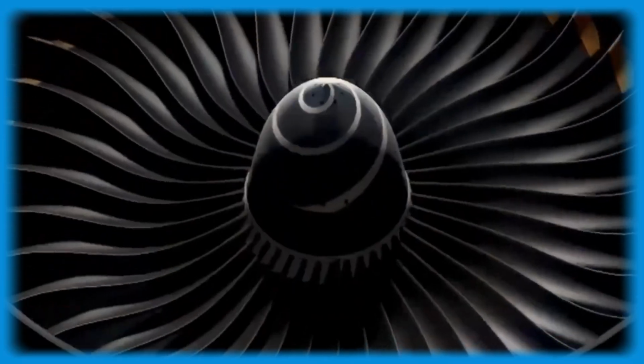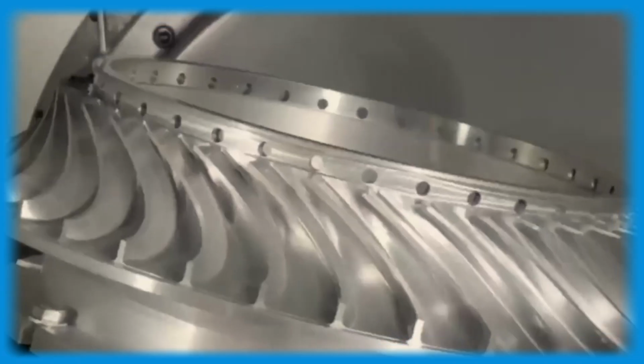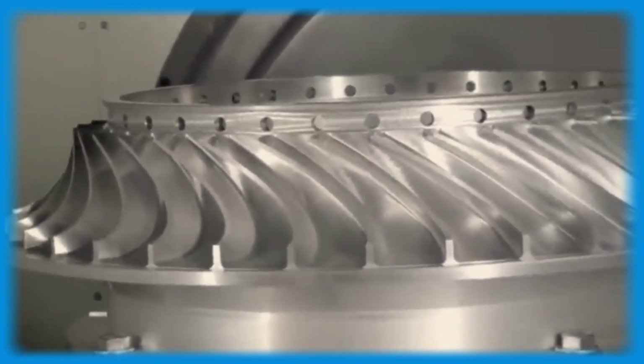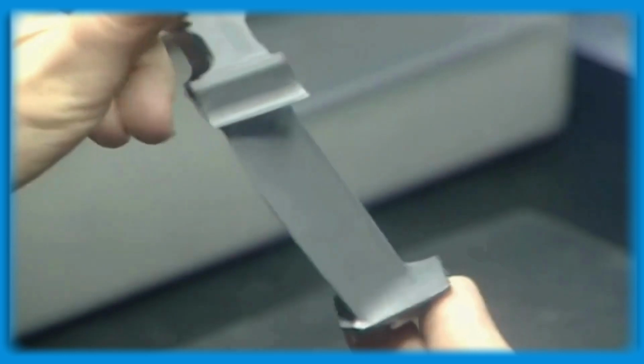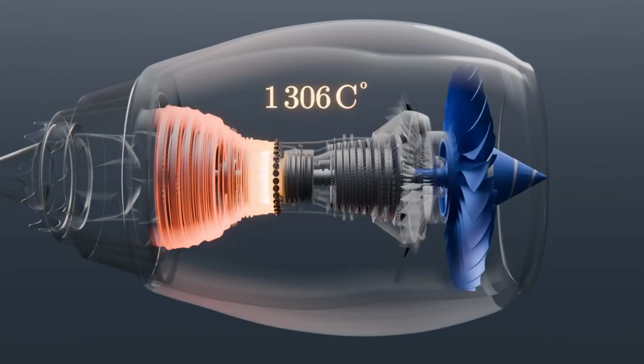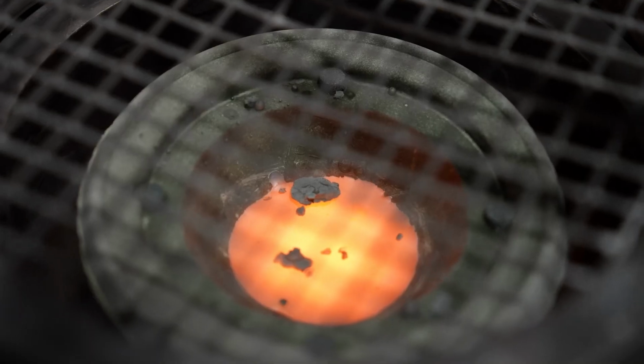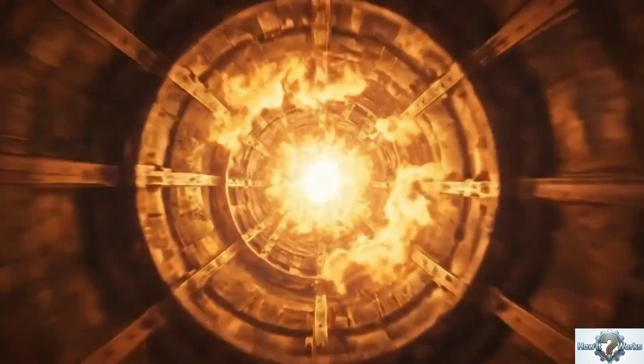Zirconia on its own is an excellent thermal insulator but is structurally unstable at elevated temperatures. It undergoes phase transformations, expands unevenly, and fractures under thermal cycling. Yttrium arrests this instability by locking the zirconia into a tetragonal crystal phase, preventing the destructive phase changes that would otherwise occur. The result is a ceramic coating typically between 100 and 300 micrometers thick that insulates the underlying metal blade, reducing its surface temperature by as much as 150 to 200 degrees Celsius relative to the gas stream.